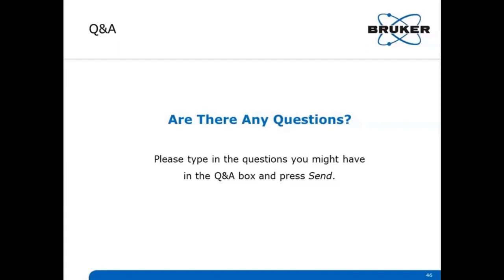But if I understand it right, you still need a WD standard with a kind of similar composition to exactly know the intensities? Or is it possible, if you have a standardless EDX quantification, to use now a single line from WD to kind of combine that? Or do you still need somewhat a standard to translate the composition into a count rate on your WDS? Yeah, for quantification by WDS, I need a standard. So I can make my own standards. So prepare some in-house standards where I collect the information by different analytical techniques. But I need some standard to be given. So for this WDS quantification, I don't need the standard for the EDS, but I need it for the WDS.